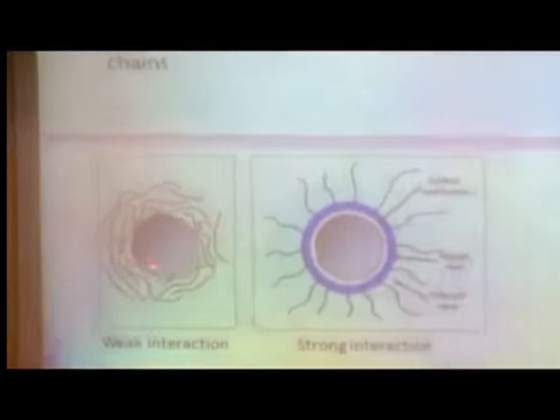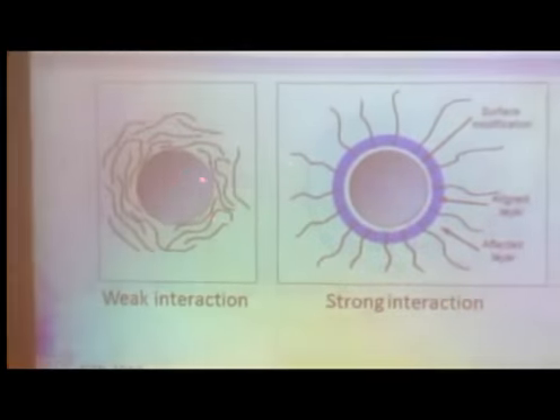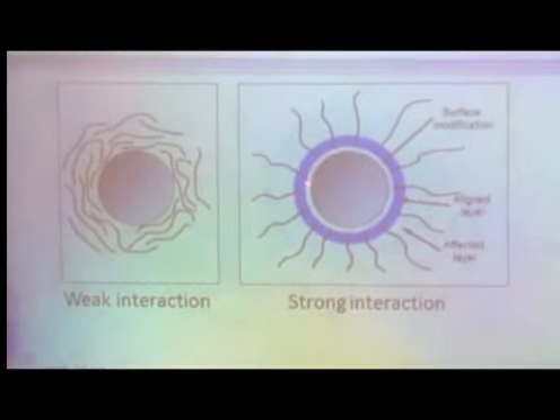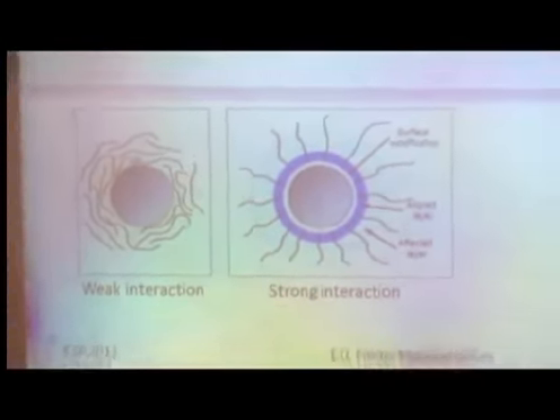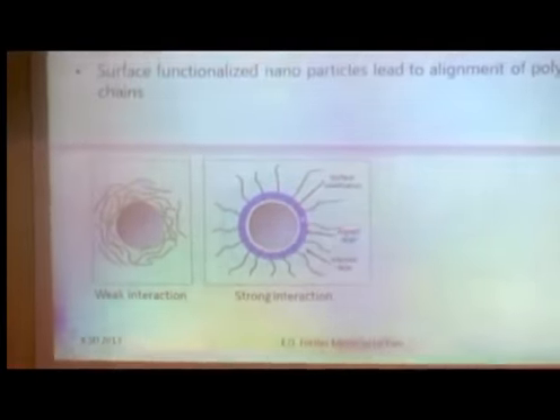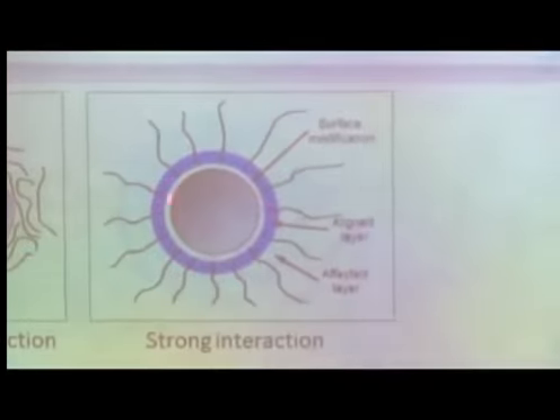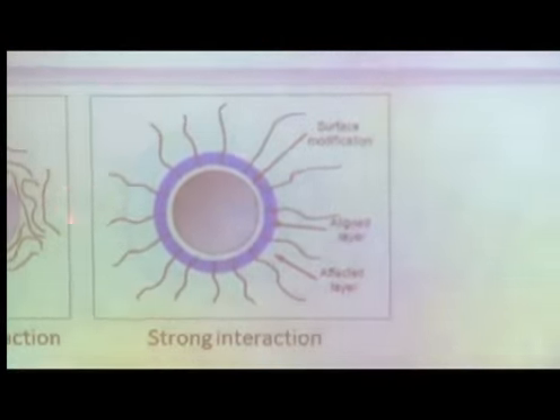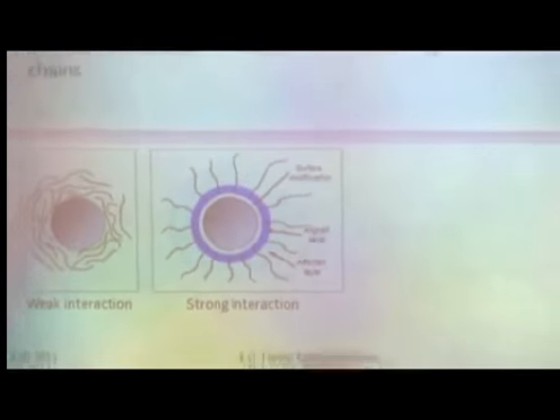You can see here that this particle has not been treated, and you see there's a very weak interaction between the polymer chains and the particle, while here, where the particles have been treated, the ends of the polymer chains end perpendicularly on the surface. So you see there's a rearrangement of chains here.